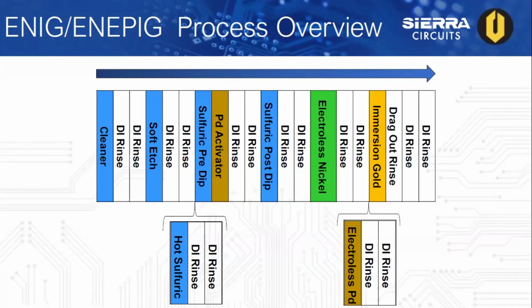Now in the green there, we have the electroless nickel bath itself. It's made up of nickel metal content, reducing agent, chelators, stabilizers, and also pH regulators. And these pretty much will all work together to ensure that we deposit our nickel layer onto our substrate or panels.